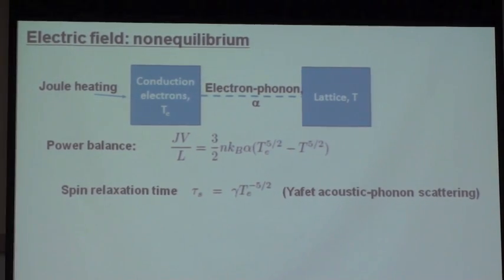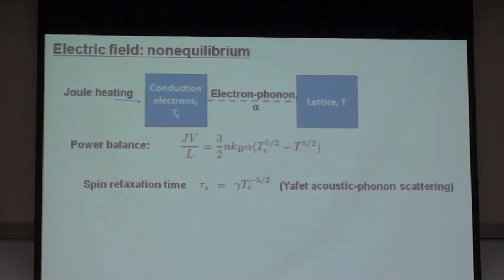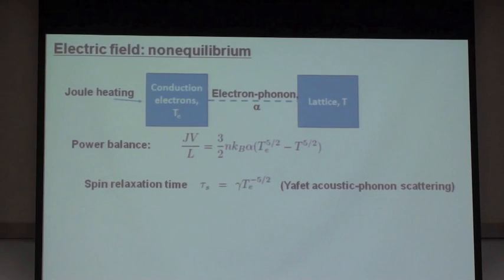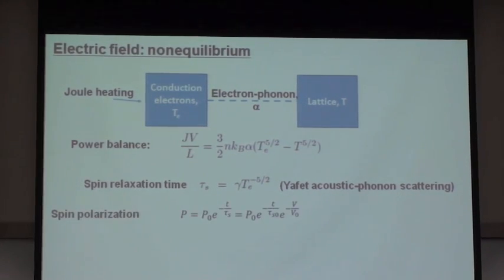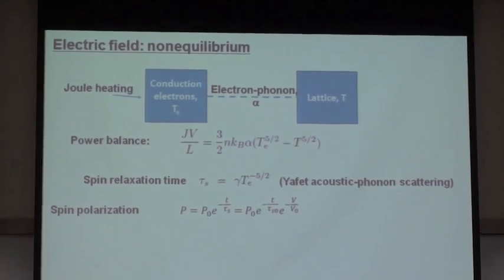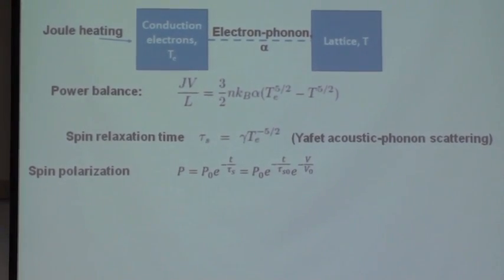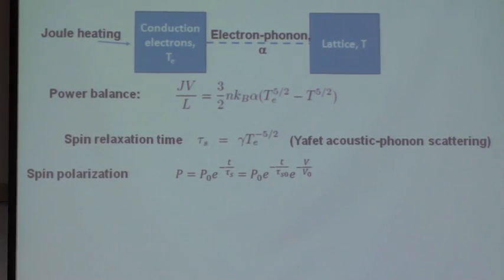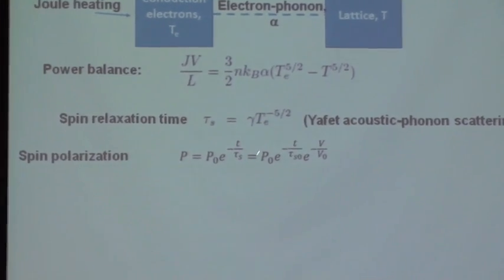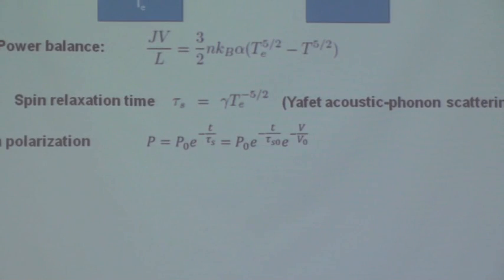We can then invert this power balance expression in order to determine the expected spin lifetime under these conditions. And when we do that, even under these very simple assumptions of this power law of the temperature that would determine the spin lifetime, what we see is an added factor here. We see the fact that not only would we expect the presence of an exponential spin decay, in other words, if it takes longer transport times due to a finite static spin lifetime, this tau S0, but we also see a voltage dependence which would give rise to a decreasing polarization under the application of very high voltages.